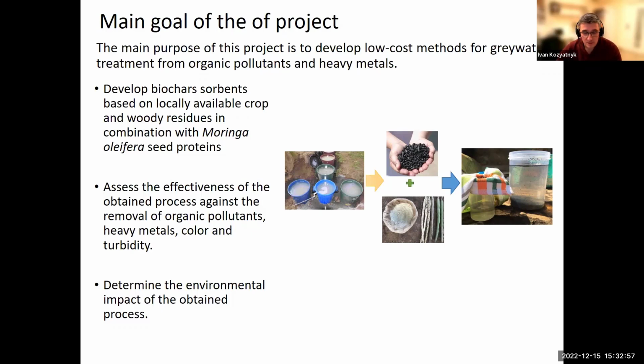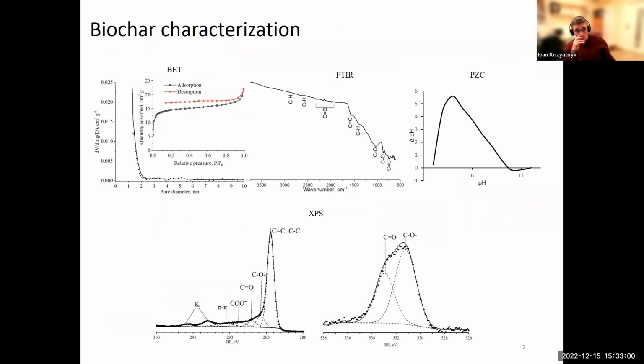further plans. So let's talk a bit about the biochar that we use in this work. It was a biochar sample produced from wood biomass from eucalyptus and macadamia in a small gasifier cooking stove. And it was taken at a farm in the Siaya district in Western Kenya. So for this work, we used the powder fraction of biochar with a size less than 0.15 millimeters.